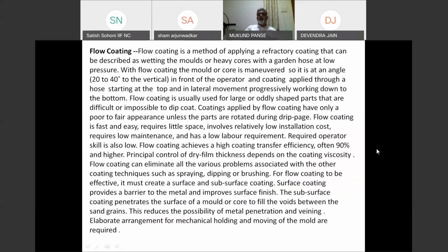It should be, as said, at a 30 to 40 degree angle so that it drops properly, and it gives a thick uniform coating, and with water-based coating, it's substantially faster.